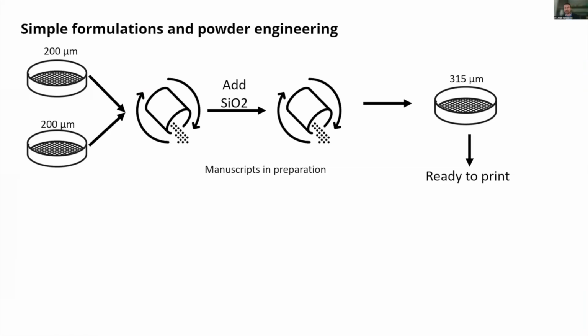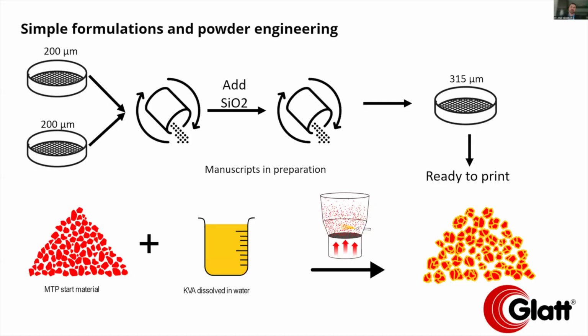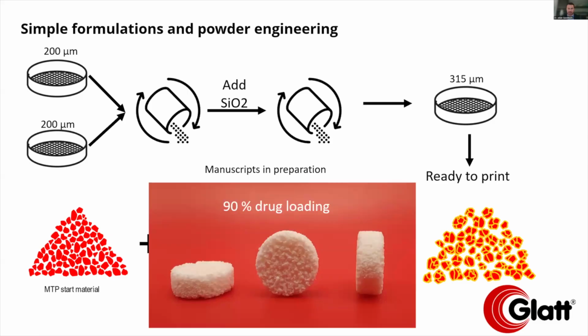And we only see very limited segregation of the powder particles during the printing process. However, that doesn't mean that we have to stick with very simple formulations. Together with the company Glatt, we are looking into the benefits of powder engineering. So in this case, for example, to increase the drug loading, because if we are only physically mixing drug and polymer, we need a quite high amount of polymer to get to hard tablets with low friability that have a certain mechanical strength. However, if we take the drug, then we dissolve the polymer in a suitable solvent, and we spray coat the particles with it. It's possible to go to much higher drug loadings because the polymer is much better distributed throughout the powder, and then also throughout the printed matrix in the end. So in this case, we were able to realize a drug loading of 90%.